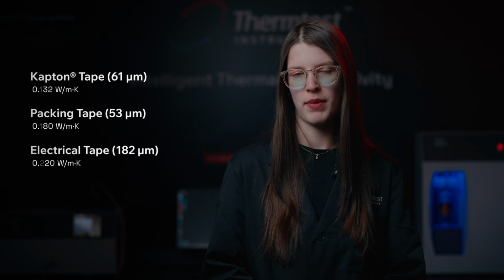Even though these tapes look similar, their thermal conductivity values were very different, with Kapton tape having an effective thermal conductivity of 0.132 watts per meter Kelvin, packing tape at 0.18 watts per meter Kelvin, and electrical tape at 0.22 watts per meter Kelvin. Different tape construction led to different thermal behavior.